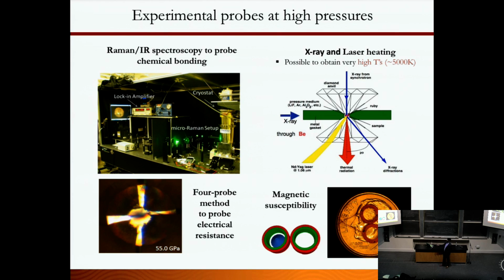And also you can put 4 electrodes and measure the conductivity. So what you're seeing here is 55 GPa. This is a reflective, metallic sample, with 4 electrodes attached to it, and you squeeze it so that you can measure the transport properties.